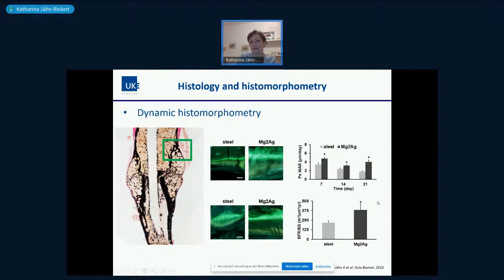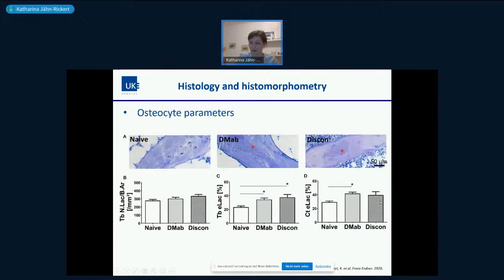So nowadays, and it's good, there are also osteocyte parameters included in bone histomorphometry. And for instance, you can count the number of lacunae that you see in the bone specimen, and then you can determine the number of empty lacunae that you see here. Here in the group of the denosumab experiment, we found quite some differences upon denosumab treatment that persisted with discontinuation, where there was a larger amount of osteocyte lacunae that were empty in the trabecular bone, but also in the cortical bone of these human bone specimens.